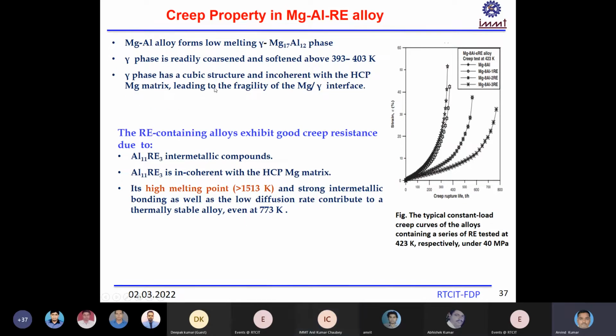So actually, the main problem was this gamma phase compound in magnesium aluminum alloys, and this gamma phase coarsens when you are heating the alloy in this range, 393 to 400 degree temperature. The gamma phase becomes coarse, and further your properties deteriorate. And this gamma phase is an intermetallic with a cubic structure, which is not compatible with the magnesium HCP structure, and the interface becomes fragile.